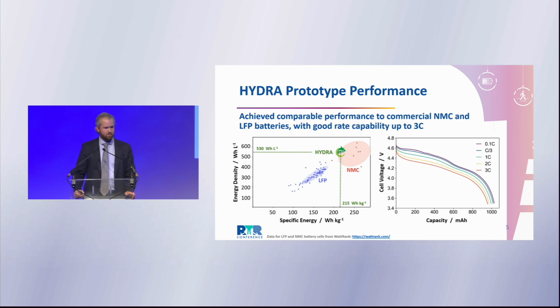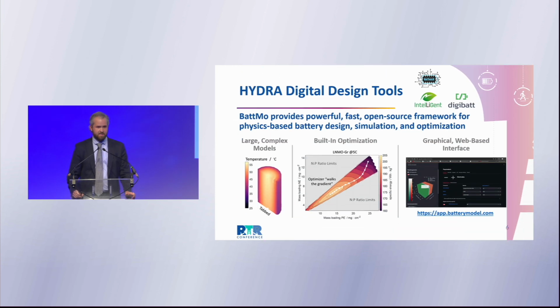Secondly, we can show some electrochemical performance on the right side, where we see discharging rates at different C rates. And there we can see that even at very high discharging rates, even at 3C, which is discharging in 20 minutes, we're still able to achieve most of the capacity of the battery in this 1 ampere hour cell. And that's very difficult to do, even in automotive cells like the new 4680 design. They start to show really significant capacity losses even at 2C. And here at 3C, we're still able to get most of the capacity. So it's a very nice achievement, and we were able to do it by employing model-based design optimization methods.